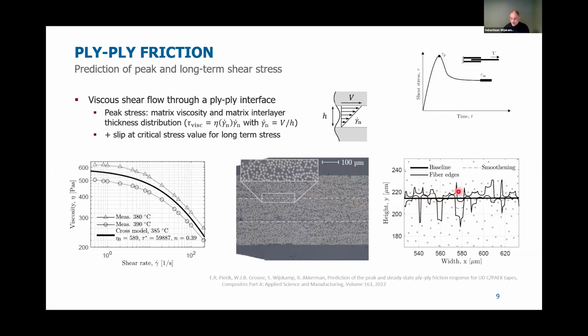We see different heights in our interlayer. So here, really, the shortest distance, so the shortest height, dominates the occurrence of the shear stress. And when all the points in the cross section have reached the critical shear stress, then there is full slip, and we reach our long-term shear stress plateau. So as we are looking at small wrinkles, that means also small displacements, small slips, then we would also like to be able to describe the full stress-strain or displacement curve. So we need a transient shear flow model.